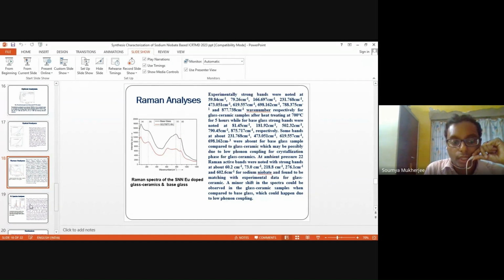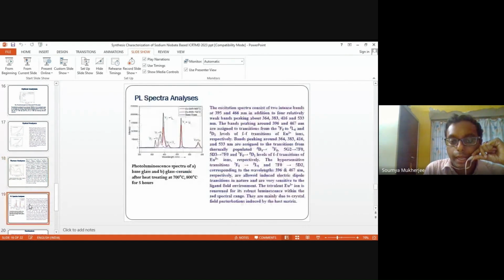And after that, we have done the PL spectra analysis, and it showed that compared to the base glass, the glass ceramic samples have a more intense peak, which is quite intense in nature. We obtained two intense bands at 395 and 460, and in addition some weak bands at 364, 383, 416, and 533. Actually, this europium doping is also creating some changes. They are creating some localized changes with field perturbation induced in the host matrix.